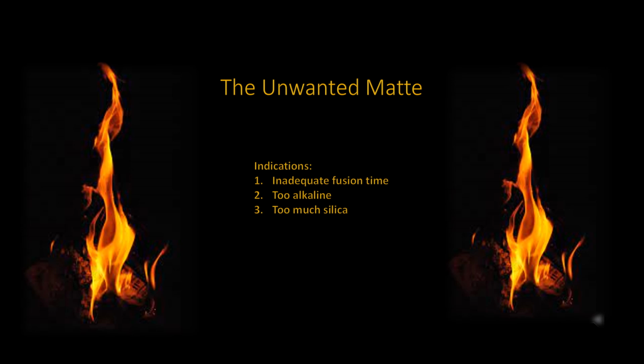Matte is that unwanted artificial metal sulfide that forms as a layer just above and at times on top of the button. The formation of this layer indicates that the sulfur constituent has not been fully removed and the base metals did not have enough time to alloy in the slag as metallic oxides. This does happen when the length of fusion time is too short and the melt is poured too early.